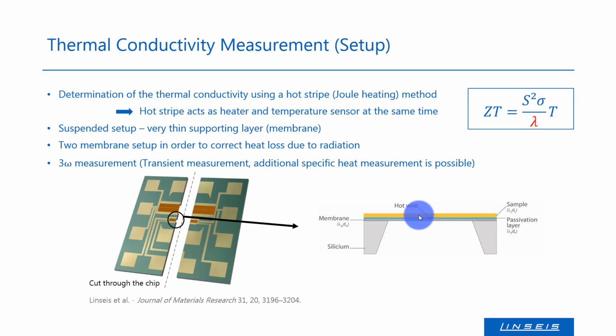The last point to mention on this slide is that we use a two-membrane setup, which allows us to account for the radiative heat loss. This is an important point, as the surface-to-volume ratio for thin films is large.